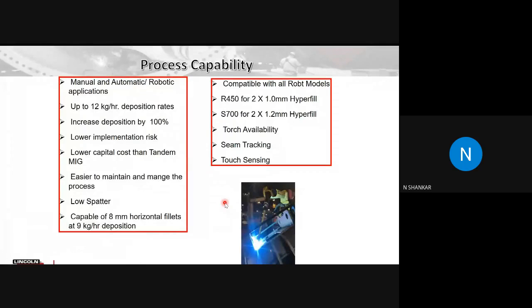If you look at the process capability part of it, it's used for both manual and robotic application. It can deposit up to 12 kilograms of weld per hour. It can increase your deposition rate by 100% compared to a single wire process. There's no implementation risk, unlike tandem. It's got a much lower capital investment compared to a tandem process. It's easier to maintain. It's got less spatter, which means you get a clean weld, and you can do an 8 mm fillet in one single pass.